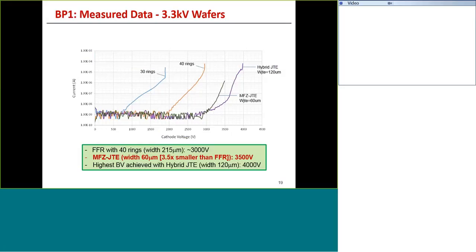So here's some results on 3.3 kV wafers. We have similar results on 4.5 kV wafers. The difference between the two is, of course, the epi layer is lower doped and thicker for the 4.5 kV wafers. So I'm only going to show you the 3.3 kV results.